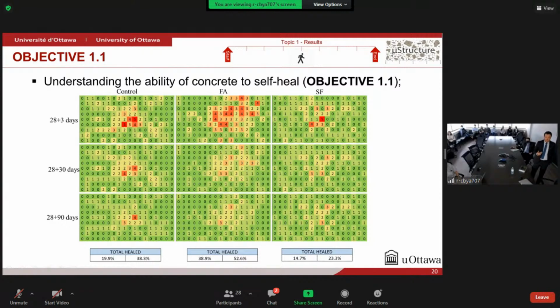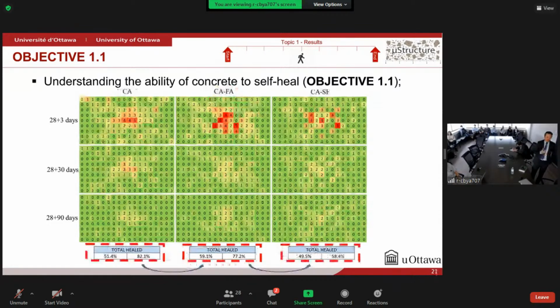This is a great value, and this proves that the self-healing of the concrete can be enhanced by the use of SCMs, as mentioned in the literature. However, if we use the crystalline admixtures, we can clearly see that the amount of cracks in the cement paste that were healed was approximately 80%. So indeed, crystalline admixtures can enhance the ability of concrete to self-heal, and this explains why we had such lower compressive strength loss for ASR affected concrete.